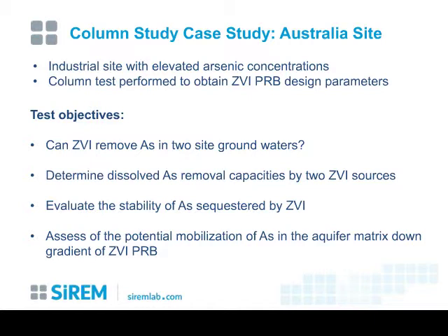They also wanted to evaluate 2 different iron sources to see if either one had a better removal capacity, as well as look at the stability of arsenic sequestered by zero-valent iron. So the arsenic was sequestered into zero-valent iron, and would it stably stay there, or would there be conditions under which it would be released? And also, because the receptor at the site was surface water, there were limitations as to where the barrier could be placed at the site. So they wanted to also look at the potential mobilization in the aquifer matrix down gradient of any barrier that they were going to put in.